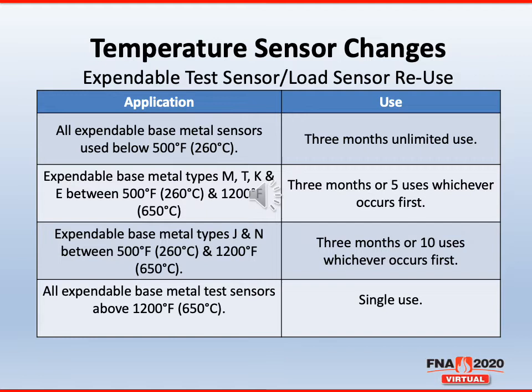All expendable base metal sensors that are used below 500 degrees Fahrenheit, 260 degrees Celsius, you're allowed to use for 3 months for unlimited use. For expendable base metal thermocouples that are type M, T, K, and E, and they're used between 500 and 1200 degrees Fahrenheit, you're allowed to use them for 3 months or 5 usages, whichever occurs first. We did give some extra usages for types N and J thermocouples when used between 500 and 1200 degrees. They can be used for 3 months or 10 usages. Any expendable base metal thermocouple used above 1200 degrees is now limited to a single use.